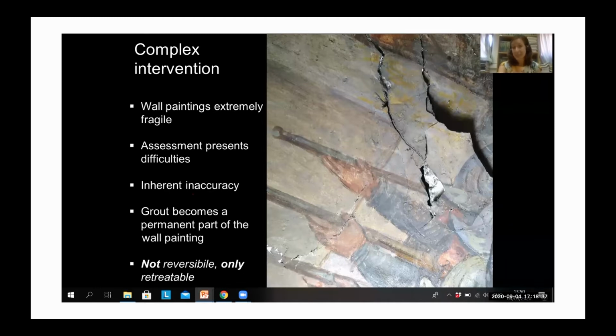On the other hand, the assessment of the delamination first and of the intervention itself presents some difficulties. Why? Because very often it is concealed, so you can't really see it. In this extreme case, you can actually see the delamination and what's behind it. But often it's not this clear, there are not many access points, or there are not cracks such as this one. So it's quite difficult to see and to assess. And because it's concealed, very often it's quite inaccurate as an intervention. There are some instruments which we can use to help the intervention and to try to understand where the delamination is, where the grout is going, but still we can't see it clearly. So the assessment is quite difficult, and it is inaccurate.